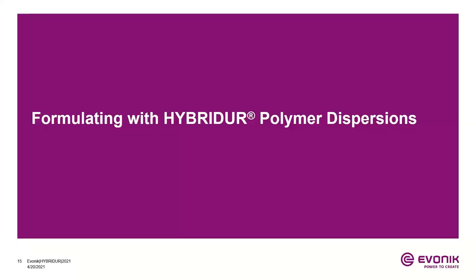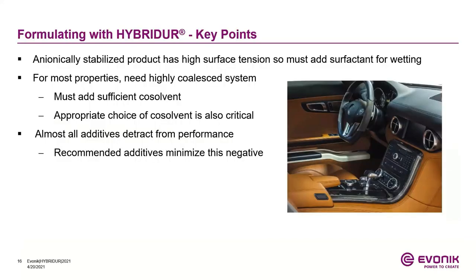Next, we will look into formulating with Hybridur polymer dispersions and how to formulate with this Hybridur one component acrylic urethane dispersions. The key points are they're anionically stabilized products. So typically, they do have very high surface tension, and the product itself does not have any surfactants in it. So in order to reduce surface tension, we must add some kind of a surfactant for wetting and film formation. For most properties to develop, we need a highly coalesced system.